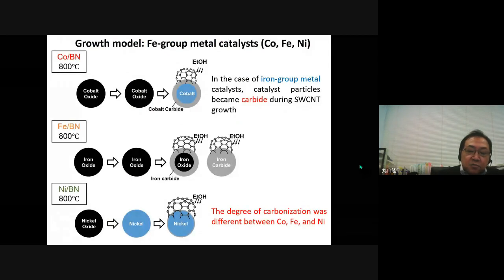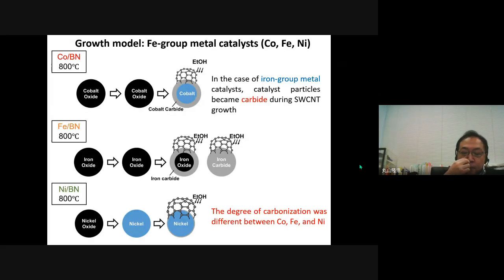These show the growth process of single-wall carbon nanotubes from iron, cobalt, and nickel catalysts. In the case of iron group elements, catalyst particles became carbide during single-wall carbon nanotube growth. However, the degree of carbonization was different. Iron was highly carbonized, while nickel was slightly carbonized. Next slide, please.